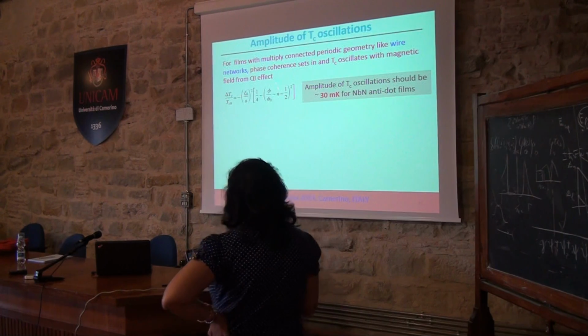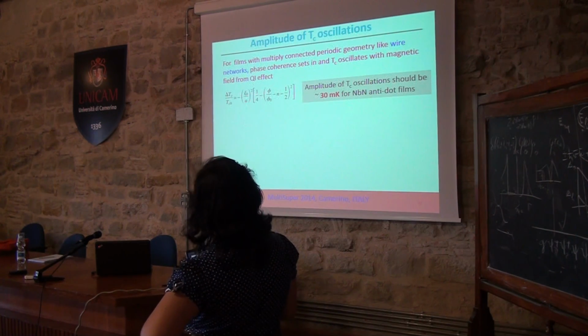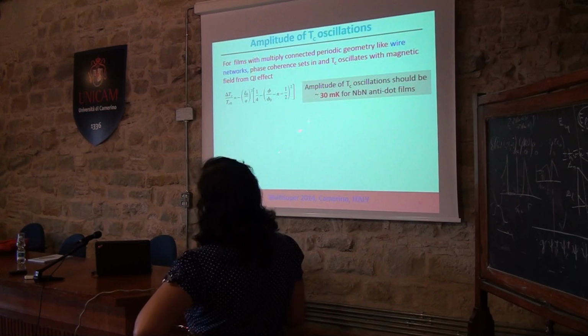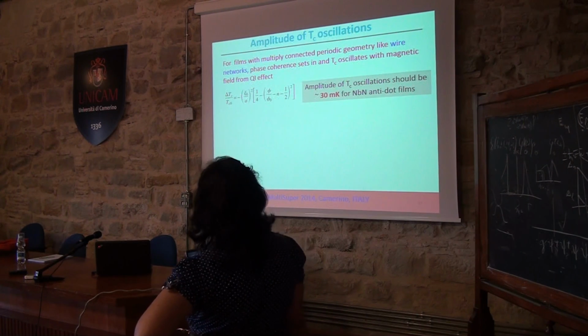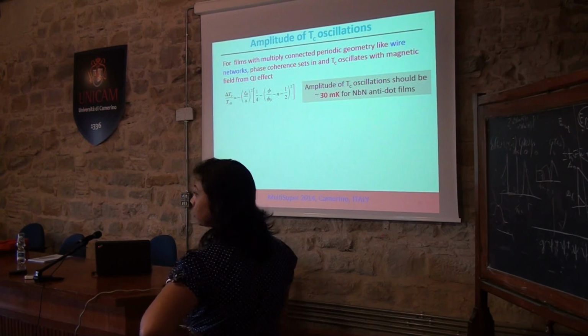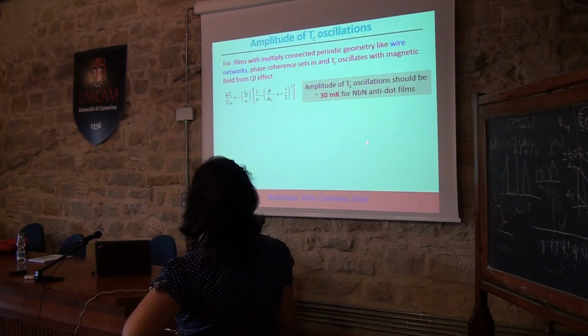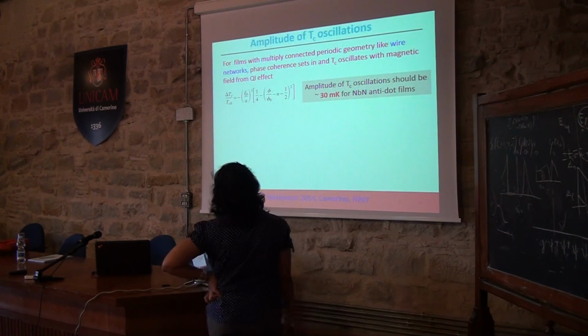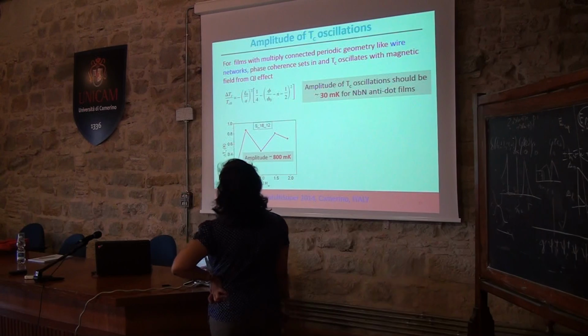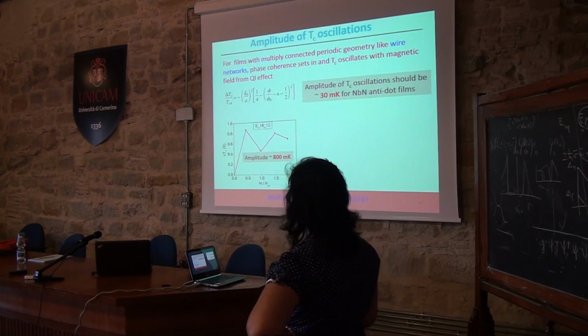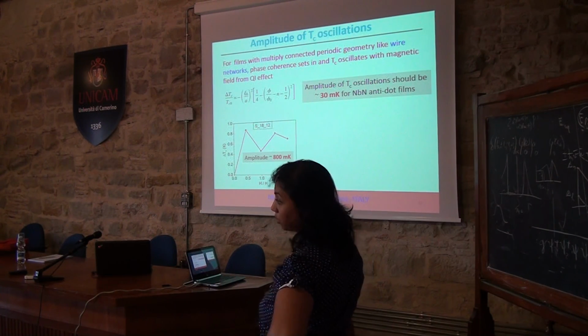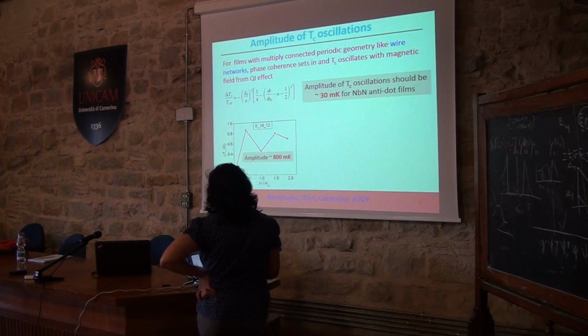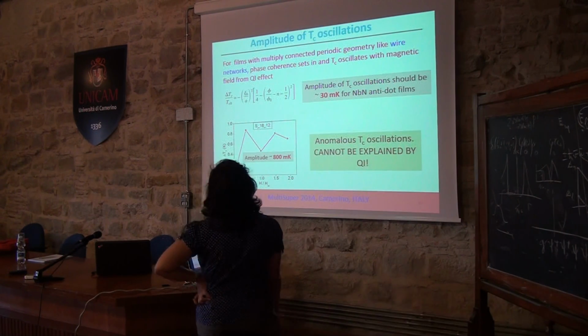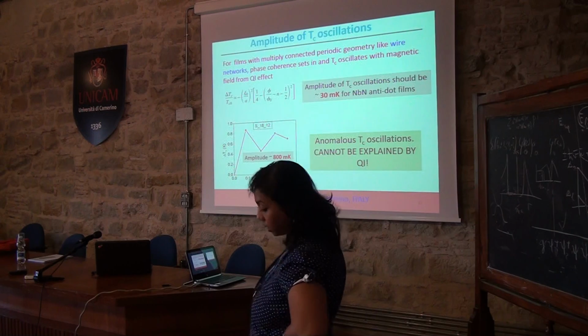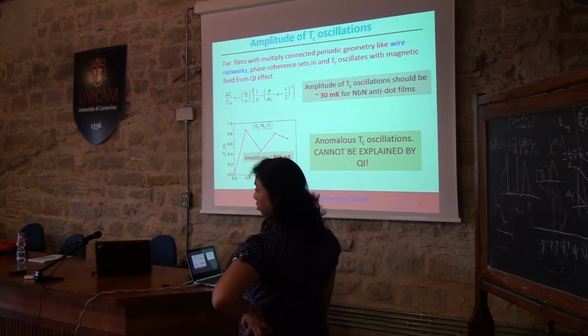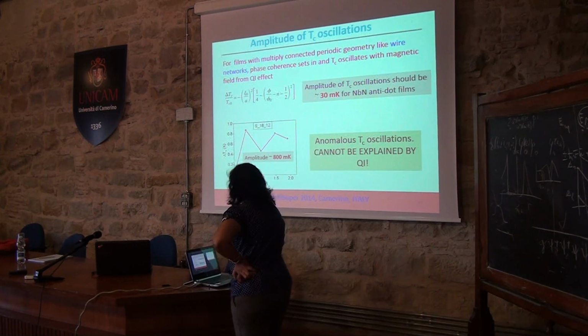Now, as I said, if you work out the amplitude of the Tc oscillations from the quantum interference effect, the amplitude of the Tc oscillation should be very tiny, just around 30 millikelvin. However, what we observe is a much larger effect. We see oscillations of the order of 800 millikelvin. So this is not really behaving. These anomalous Tc oscillations cannot be explained by the quantum interference effect.